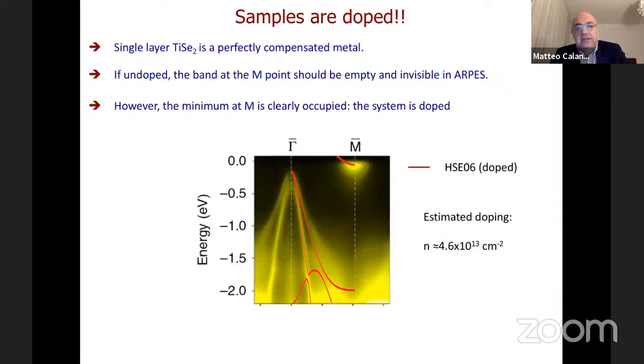You can see in my papers all the data are given, but this functional predicts almost perfectly the in-plane lattice parameter for the system. However, as I explained before, the system must have a doped band here at the M point, because otherwise the band will not be occupied. And if you try to estimate the doping by comparing HSE06 with different doping compensated by a positive background, you find that the system is doped approximately 4.6 10 to the 13 centimeter minus 2, which is a substantial doping. And this value of doping could also be wrong by a factor of 2, because it's very difficult to evaluate the doping in this way simply by comparing with ARPES. So if I change this from 4.6 to 7, I would probably still get a very good agreement with experiments.